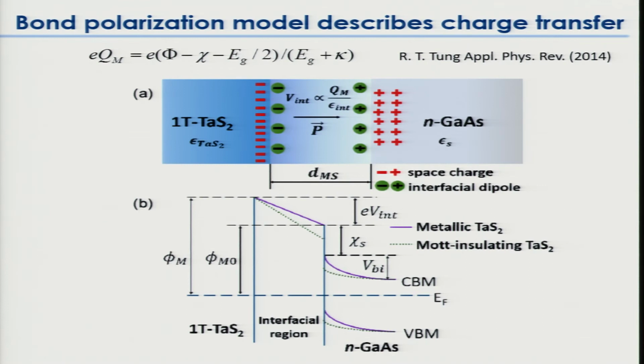Here's a band diagram, and there's an interaction parameter. What we're doing is using Ray Tung's theory about bond polarization. So there's an extra charge density at this barrier induced by the charge density waves, and we want to see how that affects the band structure. There's an interaction term, which is related to this kappa here. These are the terms we've already talked about, and this is the band gap of the semiconductor. So we have the VBI, this dashed line. There's an extra interaction term from the charge polarization, and the VBI is reduced, as we saw experimentally, okay? And this is a picture of the interfacial region.